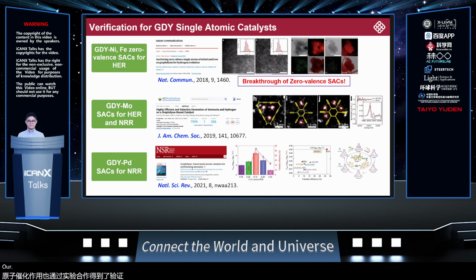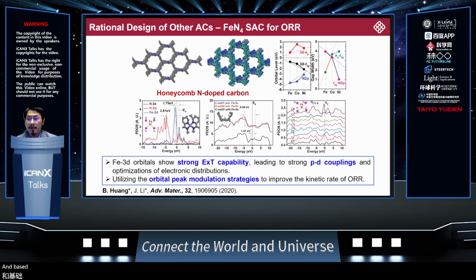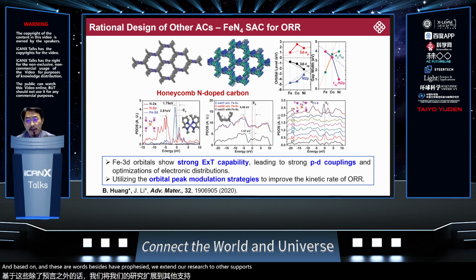Our collaborations with Professor Yuliang Li from the Chinese Academy of Science successfully proved the remarkable performances of several graphdiyne-supported SACs. These are consistent with our theoretical predictions. And based on these works, besides the graphdiyne, we extend our research to other supports. On the nitrogen-doped carbon, we collaborate with the experimental group to synthesize iron-doped SAC.